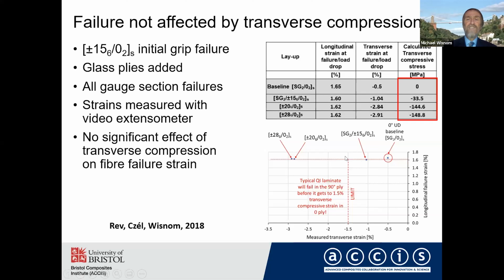And again, in practice, you wouldn't really be able to get beyond that. Otherwise, you would have failure in a 90-degree ply. If you had a typical quasi-isotropic laminate, you get failure in the compression direction in the 90-degree plies. And the compression here is quite high. We're getting up to 150 megapascals in the transverse compression, and it's still not having a significant effect.